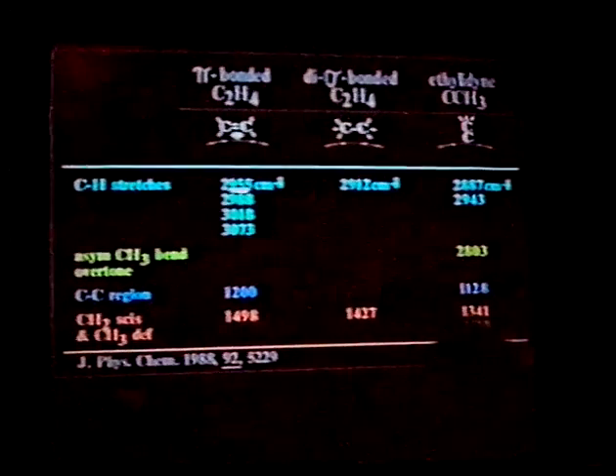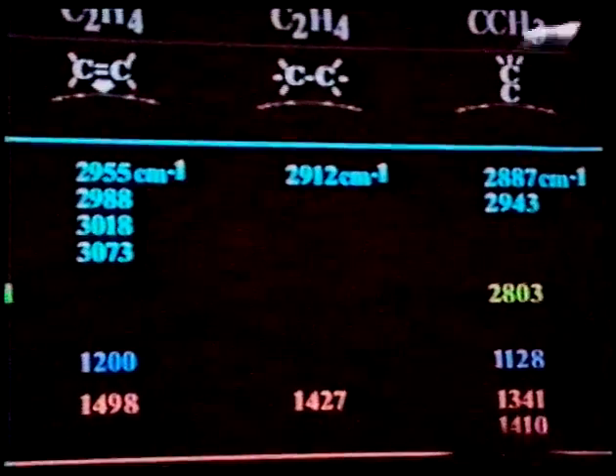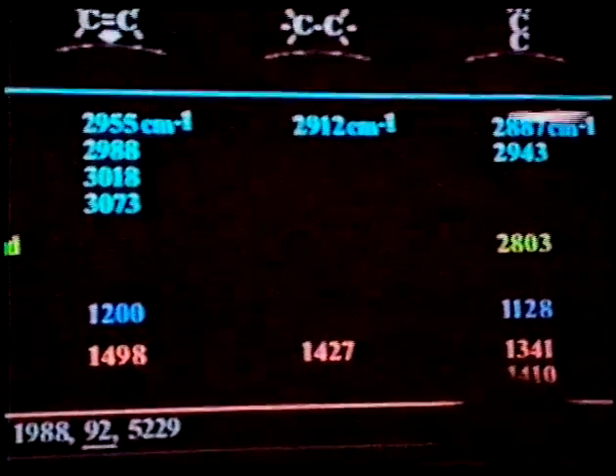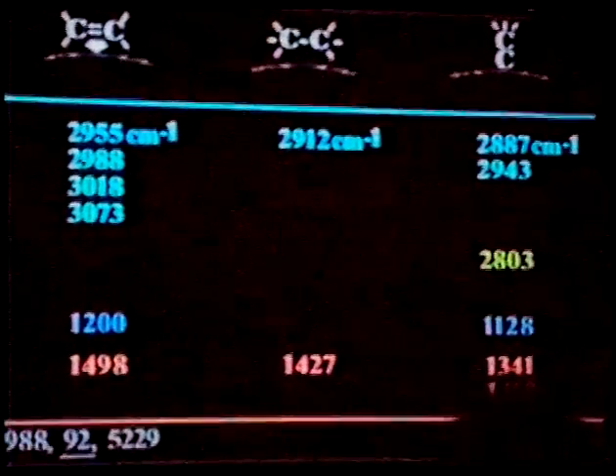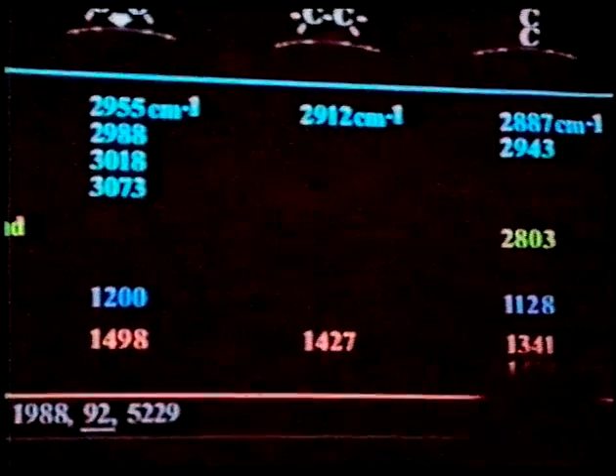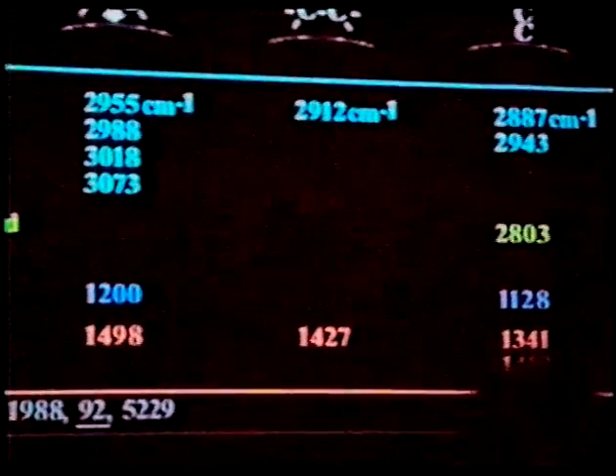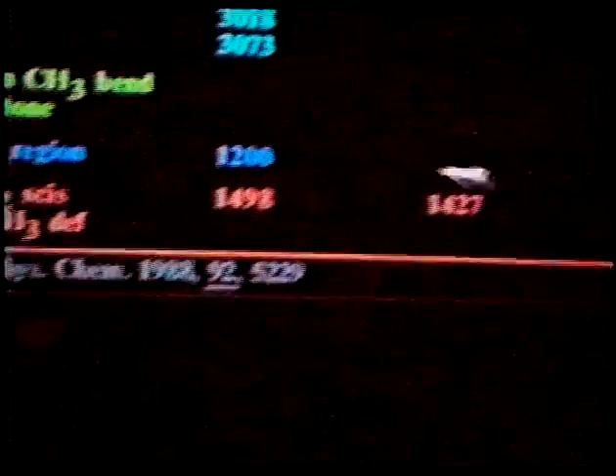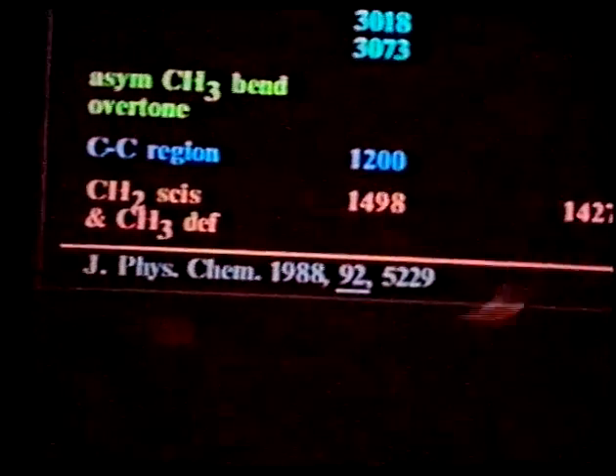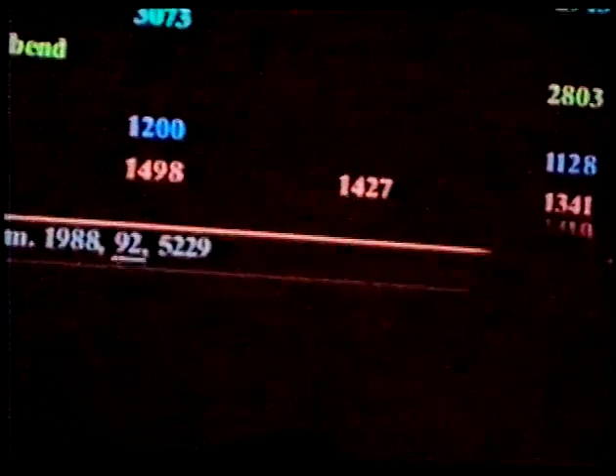One of these is in the CH stretch region, and it sits between one of the strongest bands of the pi-bonded species and the very strong CH ethylidyne bands. So this is really the most prominent band, and often when you have low concentrations of material, the CH stretching region is very difficult to detect anything with any appreciable accuracy. There is another very small band whose assignment is not really clear, and unfortunately, if we could go further down in frequency, there should be a very, very strong carbon-carbon band.